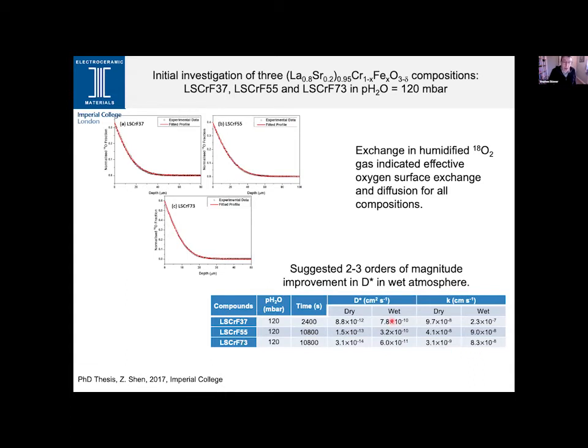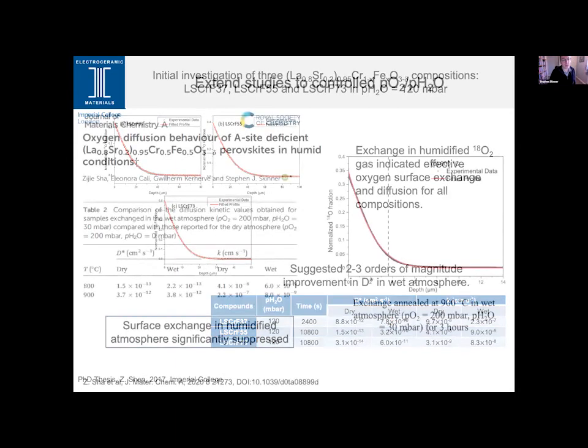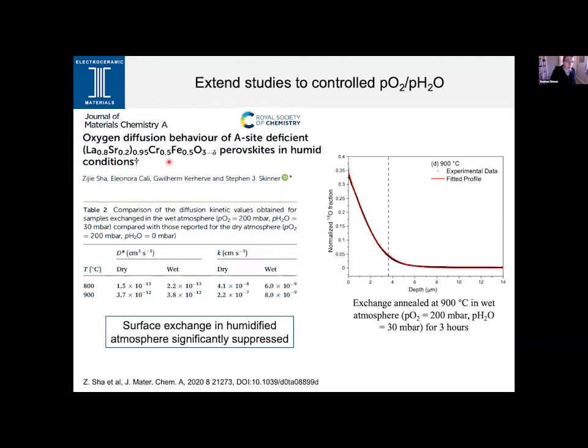This was somewhat of a surprise, so we felt that it was a useful exercise to go back and revisit these samples and control the PO2 and pH2O in a more rigorous fashion, controlling both the oxygen partial pressure and the steam partial pressure. For that, we decided to focus on one composition, the 50-50 composition. Extending that study, we were then looking at this 50-50 chrome iron composition in a PO2 environment where we had either 200 millibars of oxygen with 30 millibars of steam, or 200 millibars of oxygen with 0 millibar of steam, so the wet and the dry atmosphere.